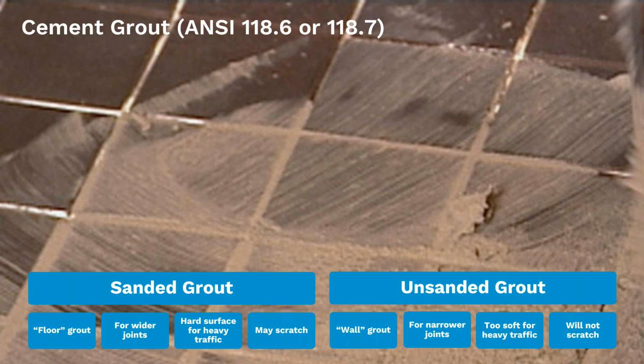When it comes to unsanded grout, typically you're going to use this more on the wall. It is for those narrower joints, so anything that is less than 1/8 of an inch up to 1/8 of an inch. It is too soft for that heavy traffic on a floor, which is actually why we recommend it more for a wall grout. And then it will not scratch that glass tile or those soft tiles that you may use within the job.